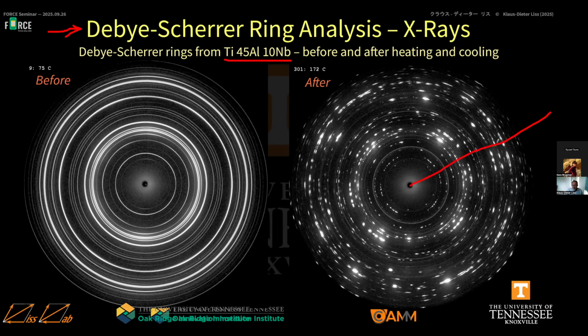Also, you go in the radius and you plot all the peaks in the radius. You can find probably all the peaks here, you can find there as well as a function of radius. But when you look to the azimuth, the azimuthal angle, you see a huge difference. The huge difference is that these reflections, these spots, they come from individual crystallites. While here on the right hand side, the crystallites are so small, and actually this is an HPT specimen, the crystallites are so small that we cannot distinguish or separate the reflections from the individual crystallites. There are so many diffracting that you get a continuous ring.